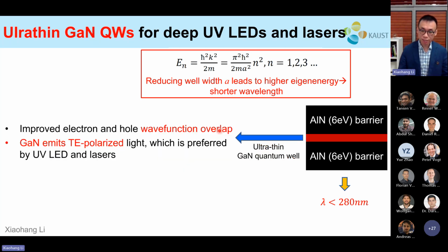In addition, having gallium nitride as a quantum well has two additional benefits. One is that you can improve the electron-hole wave function overlap because the quantum well is very thin, so you have a very weak quantum confined Stark effect. And number two is that in gallium nitride, most of the recombination happens between the heavy hole band and the conduction band minimum, so you end up with TE dominant light.